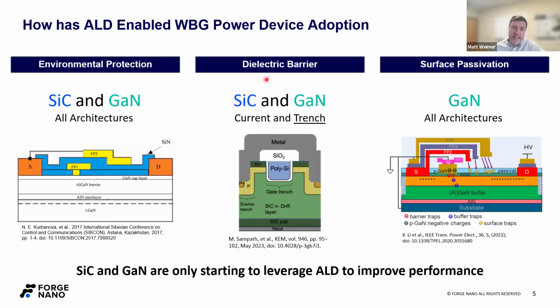All right, the next one in the middle here is a dielectric barrier. This one has really been popularized by the silicon logic space. I have a slide later that shows the history of ALD in the semiconductor industry, and this was the first big breakthrough for ALD in silicon microelectronics, being the gate dielectric. It's been adopted in a couple of places for silicon carbide and GaN, but from our perspective, the place where people have to come to ALD is in trench architectures, right? When you get features that PVD, or excuse me, CVD can't coat uniformly with a high enough quality film, and thermal oxide for, let's say, silicon carbide doesn't work, it's really ALD or nothing.